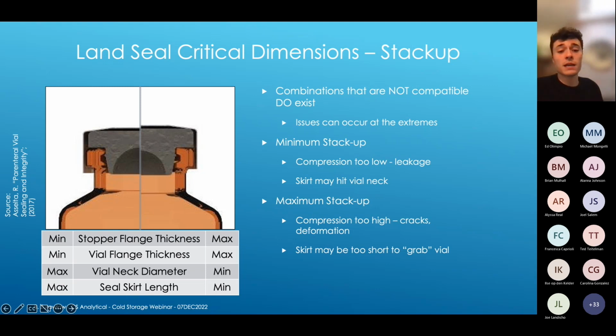Looking at the maximum stack ups, again, if we have this thickest stopper flange, the thickest vial flange, and the shortest skirt, are we able to compress that stopper against the glass enough that that skirt can tuck under and maintain that seal? Or do we get compression that is just too high, which can lead to cracks and other issues in the vial as a result of these dimensional extremes?